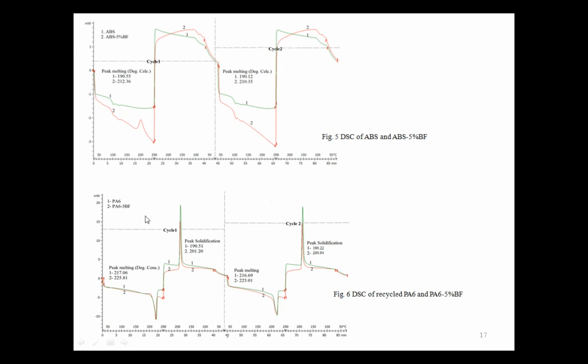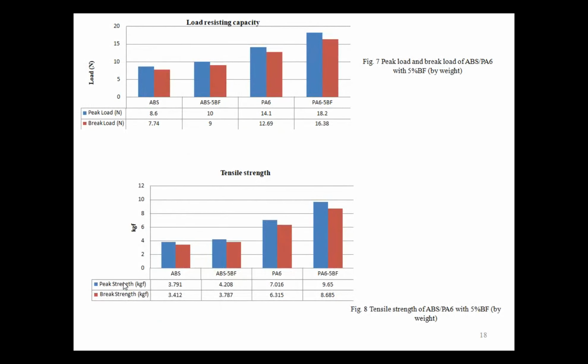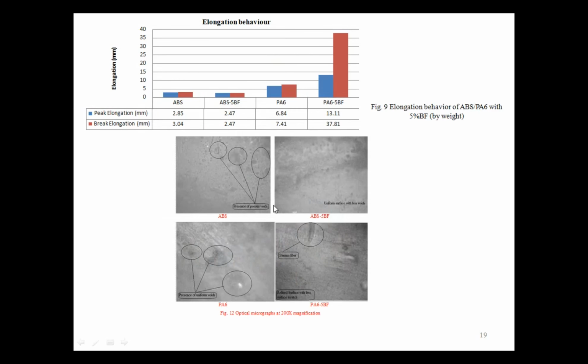You can see in this particular example also, I'm using PA6 and PA6 with 5% banana fiber. With the PA6, the maximum temperature was 217. Once I added the banana fiber, the maximum temperature absorbing capacity increased from 217 to 225. That means with this type of reinforcement of agri waste, the thermal stability of the material has improved. Then we did some mechanical testing of the printed samples. You can see the peak load and break load have significantly improved once we add the reinforcement, for the ABS as well as for the PA6. Similarly, the peak strength, break strength, and elongation behavior have improved.